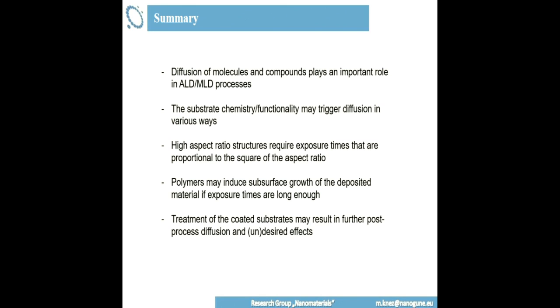If you have some of those things in mind before you start setting up your process, you may avoid spending a lot of time later on with iterations. If you just think about, oh, I need longer exposure times, and they should not only increase linearly, they should increase with the square. It's already an important point to know. So, high aspect ratio structures really need a long time.